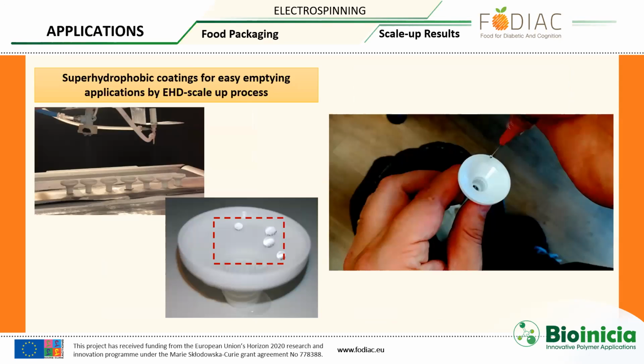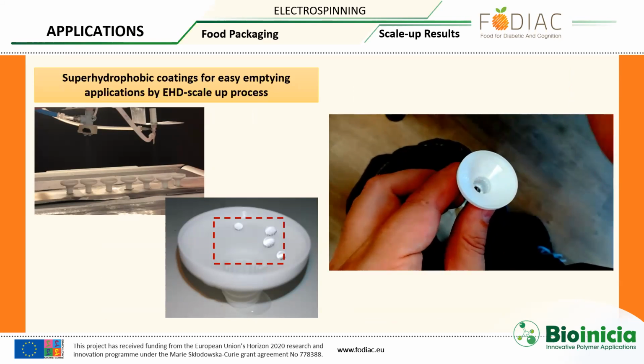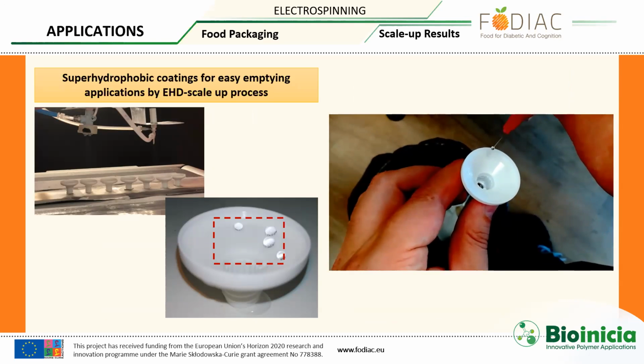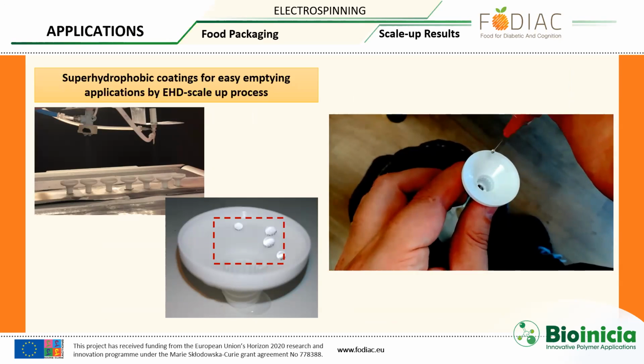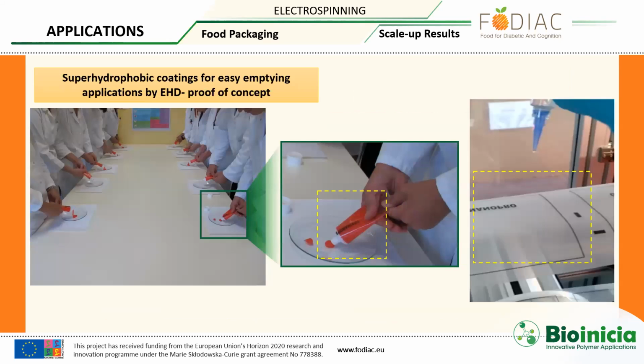Obviously, because we need a lid for these tubes, we also tried to coat non-planar substrates, in this case these lids, which was very tricky, but in the end we managed to coat them homogeneously and get super hydrophobicity on these lids as well. As a proof of concept, we built these tubes, put a water-based gel and also ketchup into them, and we created a panel where people pushed it through to the end, like you would when you are running out of your cream or your gel and you want to take it all out.